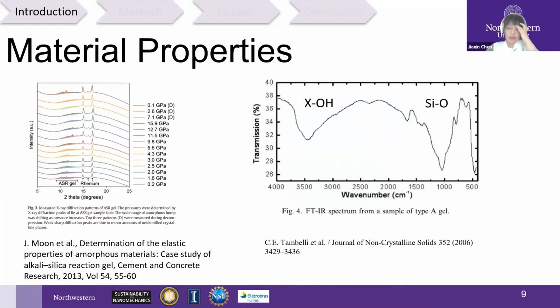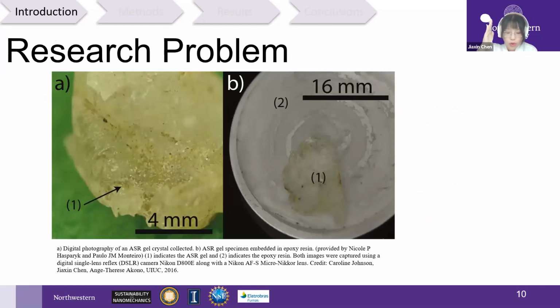For the ASR gel crystals from the same Furnas Dam, to have an overall idea of these materials, previous studies have shown that material properties have been characterized by Professor Moon and Dr. Nicole, Professor Monteiro's group previously. X-ray diffraction results showed amorphous properties. In addition, Dr. Tambelli used Fourier transform infrared to identify chemical groups of the ASR gel crystals. Definitely more details can be found in their papers as shown in the reference. But our group focuses on the fracture behavior of the alkali-silica reaction gel.